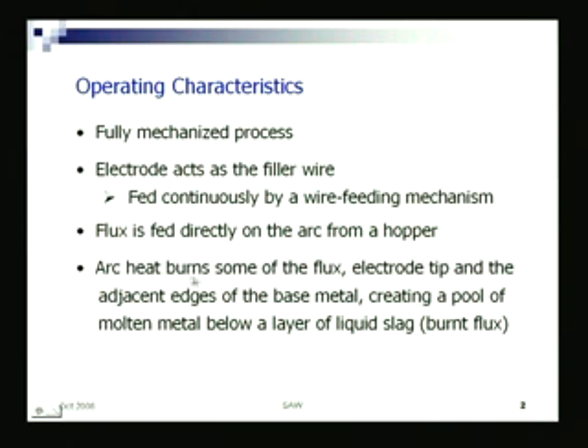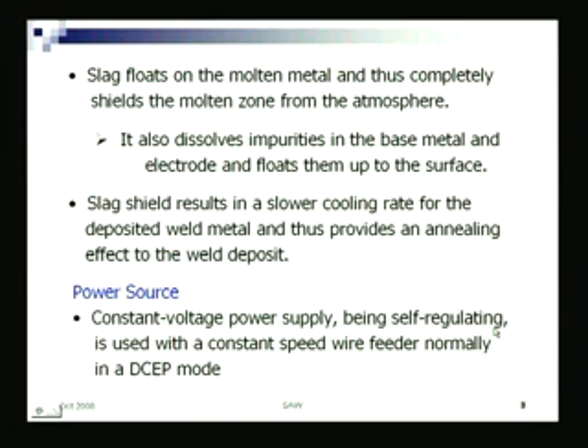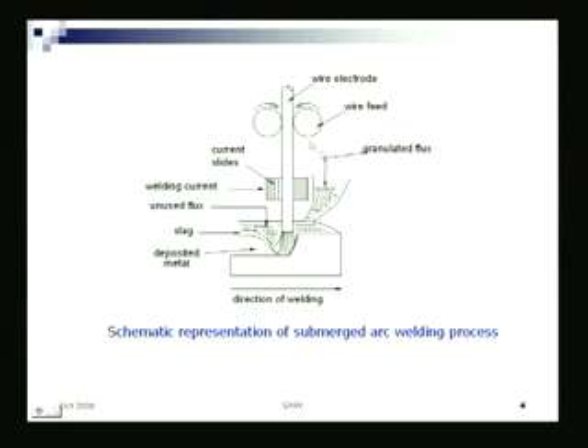The arc heat burns some of the flux, right. The electrode tip and the adjacent edges of the base metal are melted, creating a pool of molten metal just below the arc, which is covered by a liquid slag. That liquid slag is nothing but the burnt flux, right. So, let us schematically show it like this.